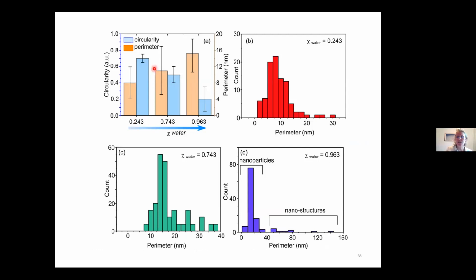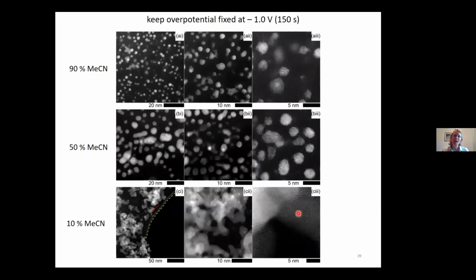And so we can represent this in this way. You can see that as you increase the amount of water, the nanoparticles are becoming less circular, they're increasing in perimeter, and you're getting more of these dendritic type structures evolving. What we can do then is move and go to longer times, and we see very similar events occurring. So we're not doing identical location here, we're just looking at different areas